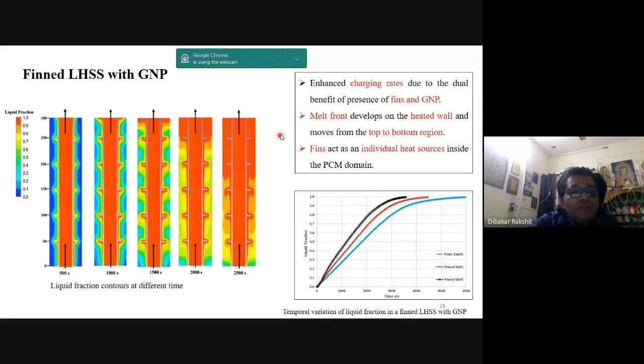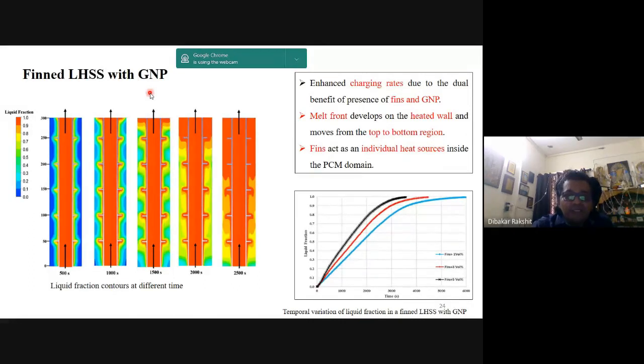Then we introduced the graphene nanoplates also, to increase the efficiency of charging and discharging of the thermal battery. We found that by this dual behavior of having the graphene nanoplates with the fins, the charging rates of course increased, like the rate at which the system was getting charged. And then we also found that the melt front develops on the heated wall and moves from top to bottom. Of course, it will happen that way only.